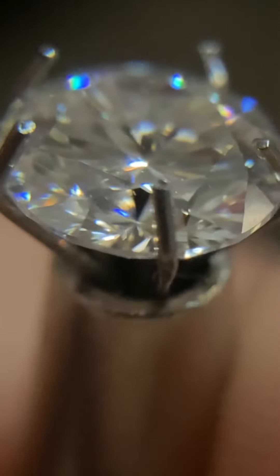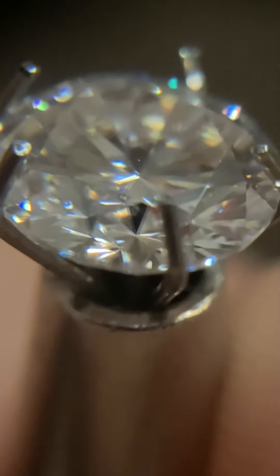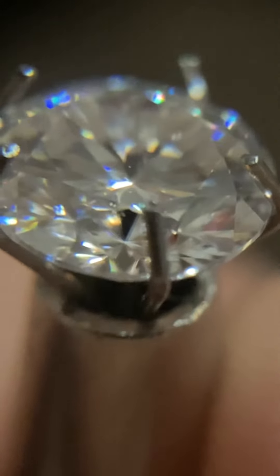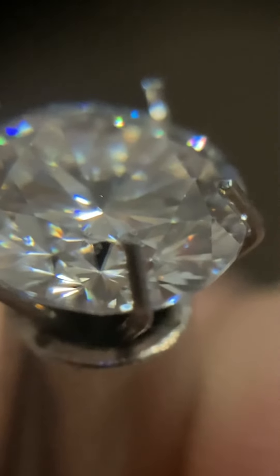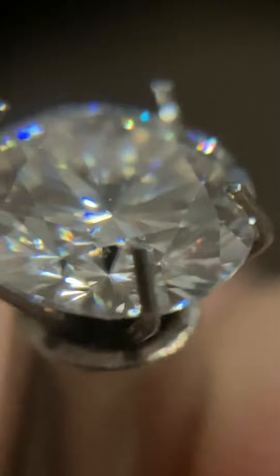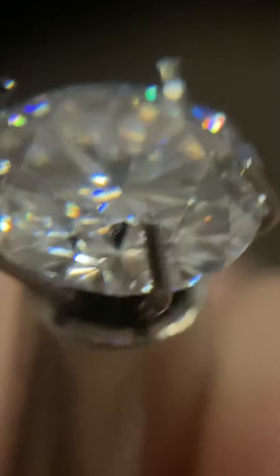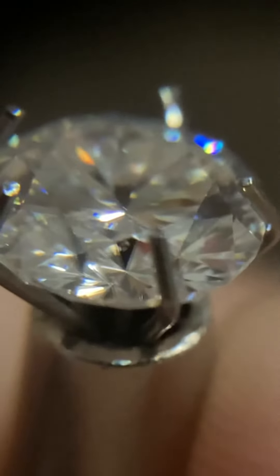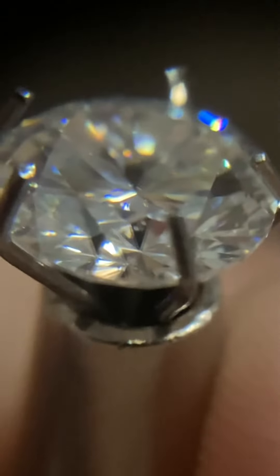There's a prong, and to the left of the prong you can see that pavilion main — it looks like a kite. You can see both sides; it looks kind of blurry. That right there is a clear definitive indication that you do not have a singly refractive gem. I'm going to be getting some natural zircon, and you can face-up see the birefringence — the double refraction.